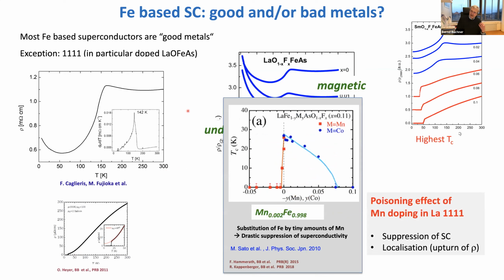which we have in these materials. Let me highlight another point. What's also quite characteristic for these 1111 type systems is something which people call the poisoning effect of superconductivity. So you start from an optimally doped lanthanum 1111 type system, you plug in 0.2%, that's basically nothing, of manganese, and you destroy superconductivity. And it's not only superconductivity which you destroy, you can have a closer look at these publications. It's the normal state which drastically reacts to tiny amounts of disorder. Again, telling you that these systems are far away from being easy, simple, good metals.